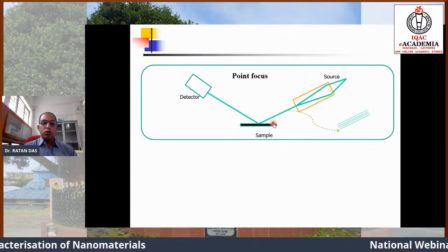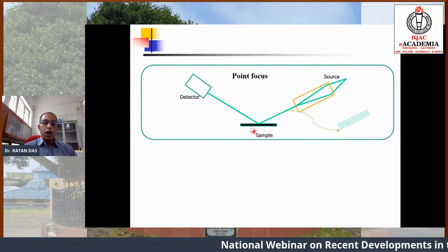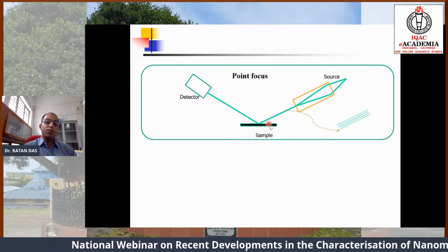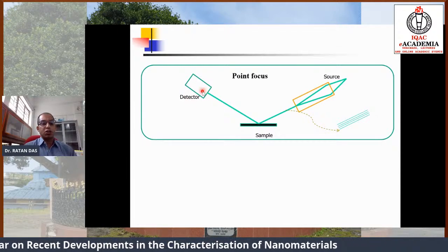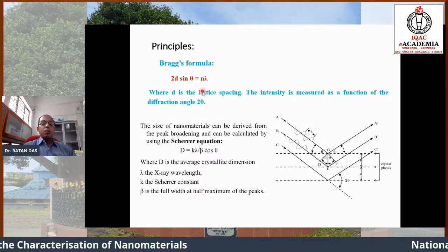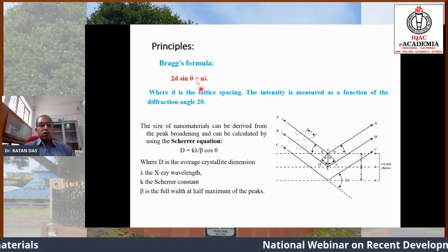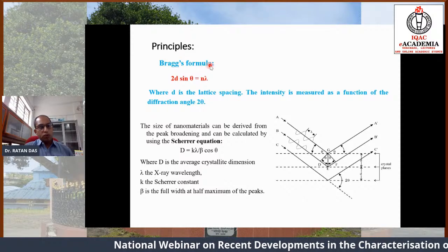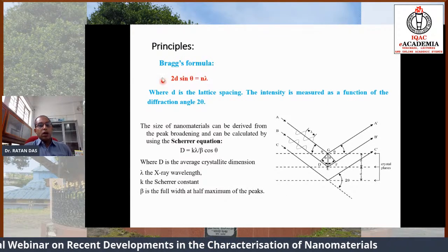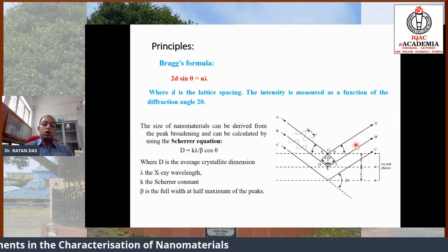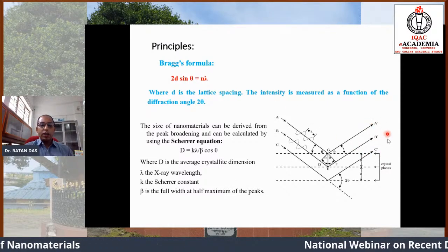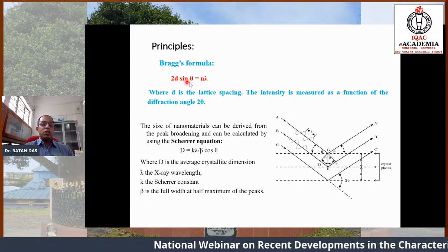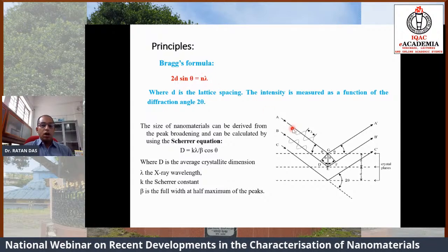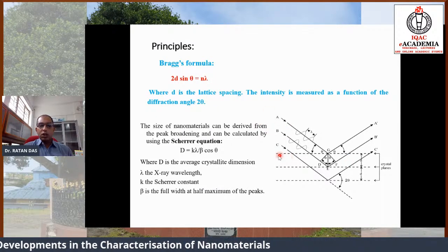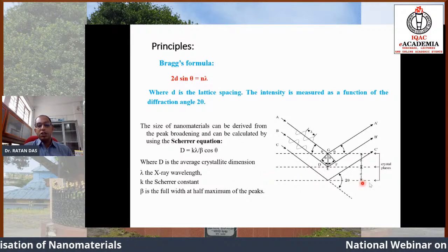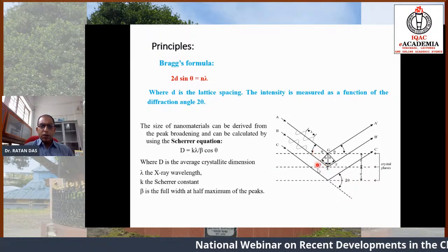Now here, see, from the source light rays fall on the sample, and then go to the detector after scattering, and the detector measures the diffraction pattern or scattered pattern. So the principle of X-ray diffraction is nothing but Bragg's formula. We know in the diffraction pattern, this Bragg's formula tells us where we shall obtain the higher intensity rays. So it is 2d sin theta = n lambda. n is the order of the reflected rays. d is the lattice spacing. You see here those straight lines are the lattice spacing. All of us know this, and these are the planes.